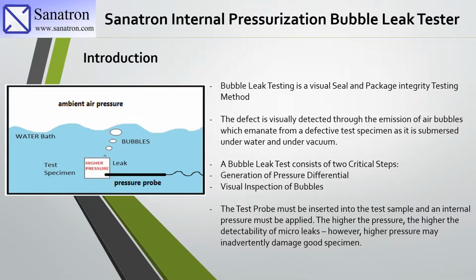With regards to the internal pressurization test, since the pressure inside the specimen is the same as the ambient pressure in most cases, a way to bring higher pressure into your specimen is through a pressure probe, where the pressure probe is inserted into the test specimen. Generally speaking, the higher the pressure, the higher the detectability of the leaks, so you'll be able to detect smaller leaks. But on the other hand, a higher pressure can also inadvertently damage your good specimen. So there is a trade-off here, a balancing act, and that's something that you will have to determine internally while you're doing your tests.